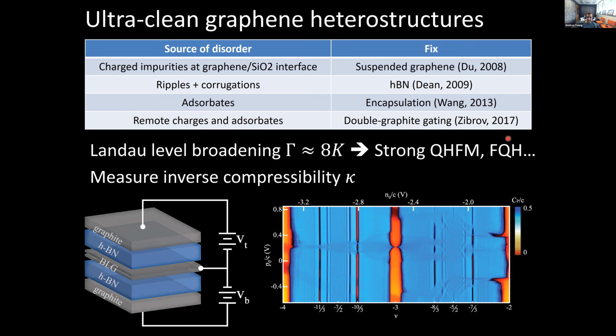And then more recently, just in the last 5 years or so, we really came to understand that actually the limiting factor was patch effect from deposited, typically evaporated metal gates, and those metal gates had grains, and those grains have different work functions, and that was actually a leading source of disorder. So we moved to using single crystals of graphite as the gate dielectrics for these types of materials. And now we have these all van der Waals type of devices.